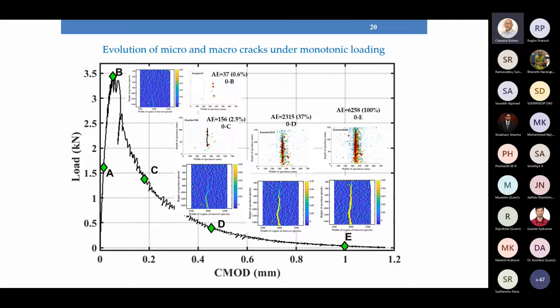What it means is, after the peak is reached, micro cracking takes place, and for all these micro cracks, we see that there are different size markers shown for the events. So high energy events are increasing. That means a micro crack is coalescing and forming a macro crack, and final failure takes place due to the propagation of the macro crack, which is also seen in the digital image correlation on the surface.